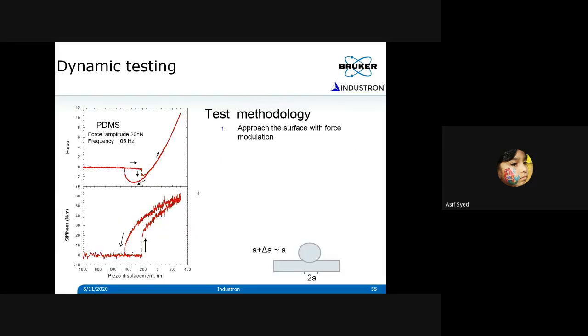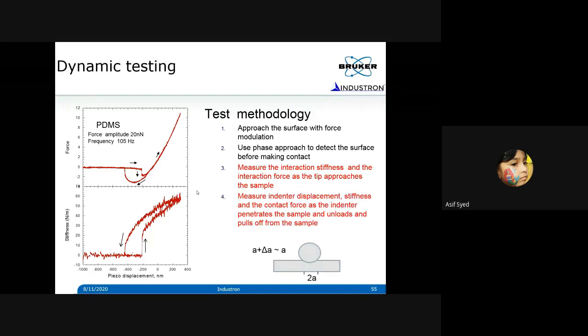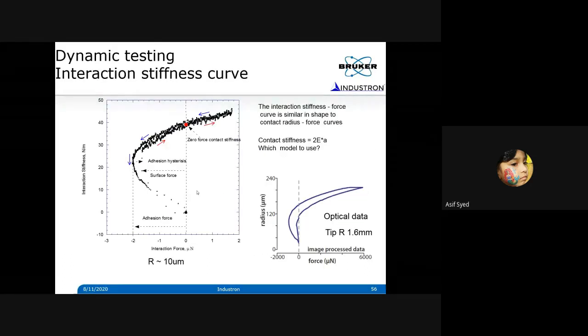Using the same approach, we can also measure the mechanical properties. For example, not only measuring the load-displacement curve, but also measuring the stiffness as the tip approaches and makes contact. You can measure the stiffness as a function of approach distance. And if you plot that, you get this curve, which is basically interaction stiffness as a function of interaction force. By the model that I presented earlier on, you can fit the model to this curve and you can accurately measure the modulus of the material. This is another way of measuring the modulus of the material for soft materials.